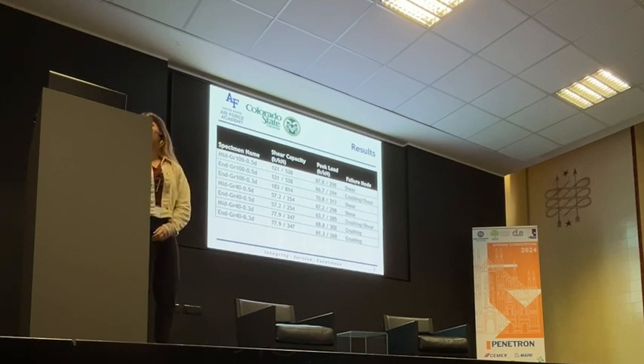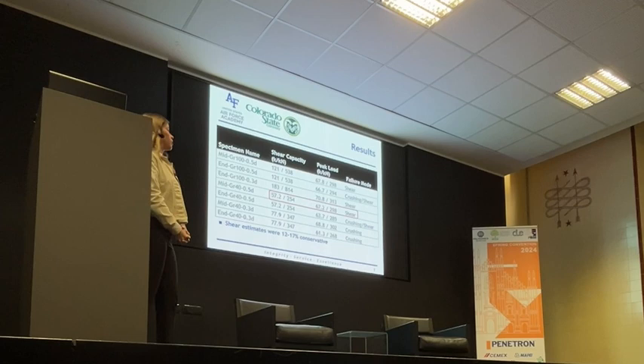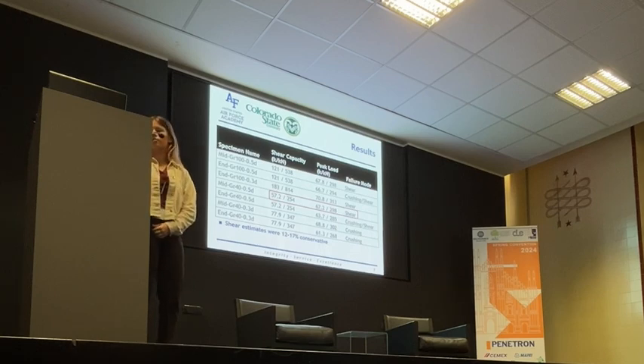An interesting thing to note would be the one that's outlined here in red. The failure mode was shear for this one, even though all of them were expected to fail in crushing. And by comparing the peak load from experimental results and the shear capacity that we'd estimated, we find that these values were 13 to 17% conservative.